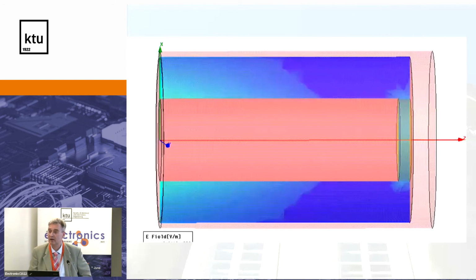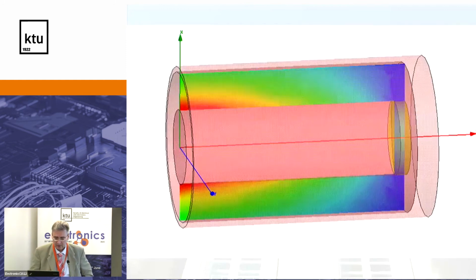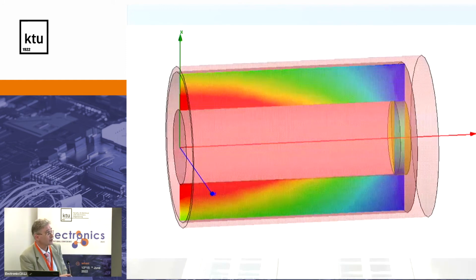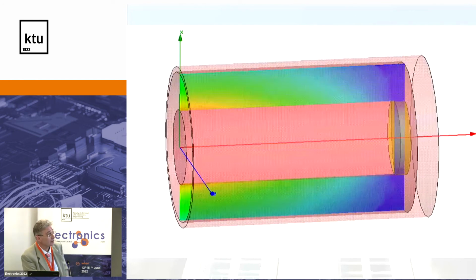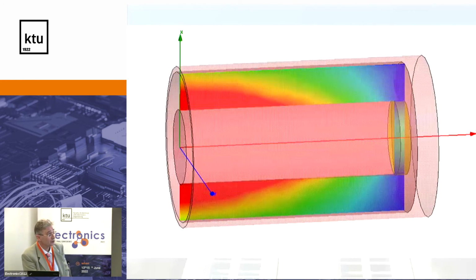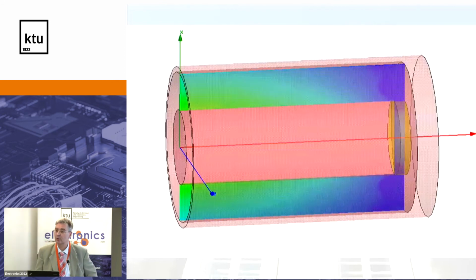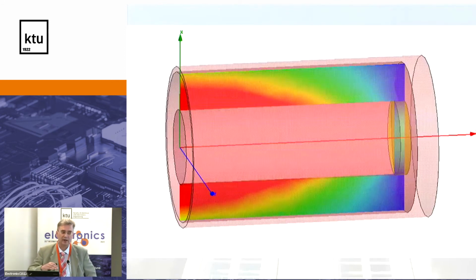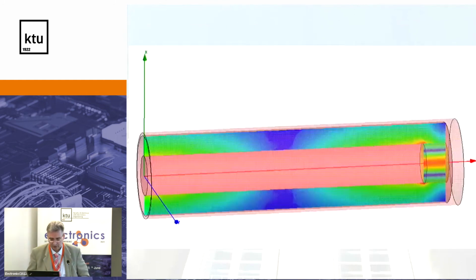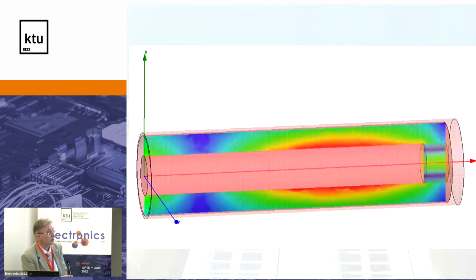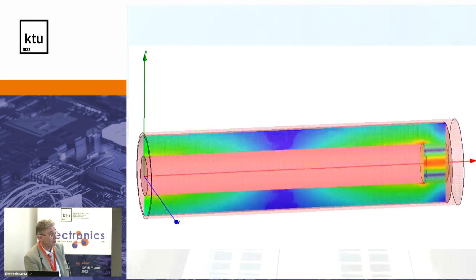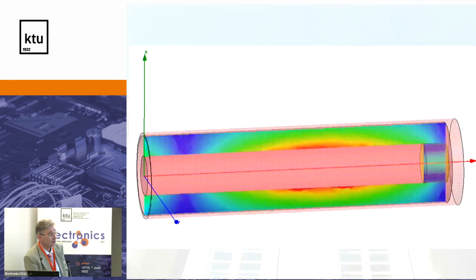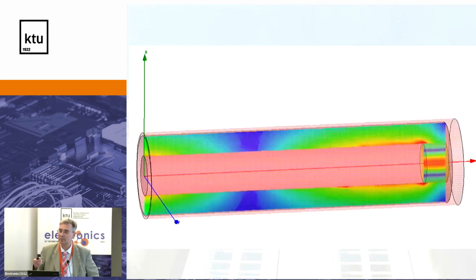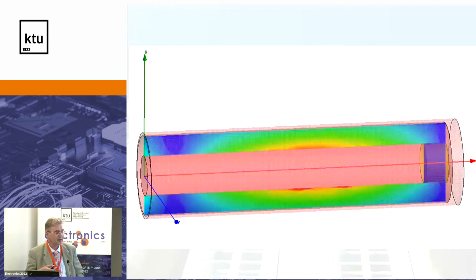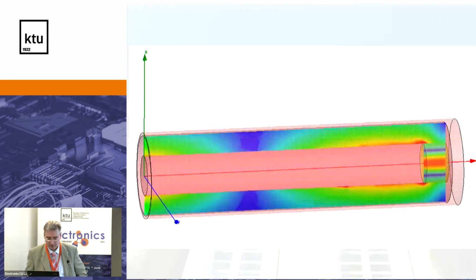We see that when we have small dielectric permittivity, firstly, we try to model somewhere in that region. And we see that we have excellent agreement and the capacitor model is working. You see simply the color is the same. So the electric field is homogeneous. If we increase slightly the electric permittivity, we can see here at the end that we have already different colors. So this distribution is not homogeneous anymore. So we are getting fake results. And if we increase the electric permittivity further, we can see that the picture of the electromagnetic field is completely different. And here are the different modes generated inside the material. Even more complicated.